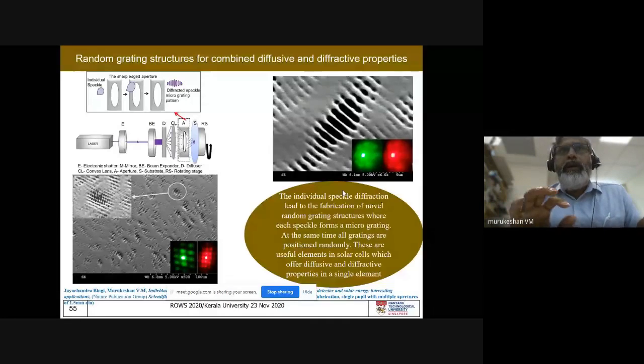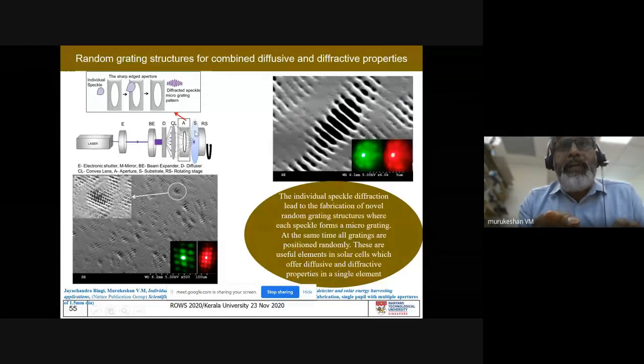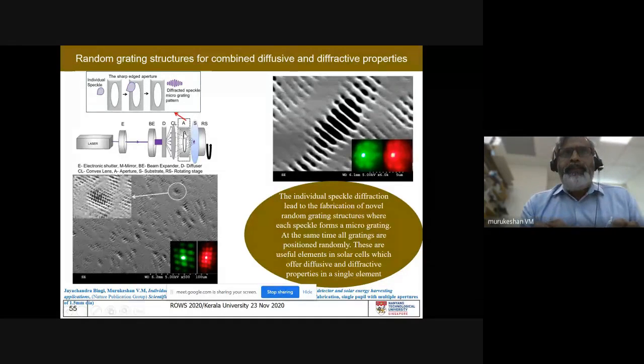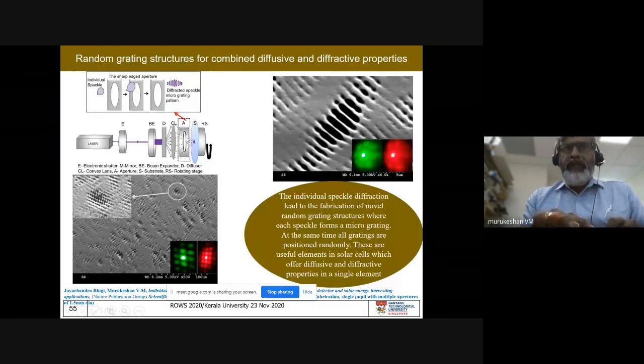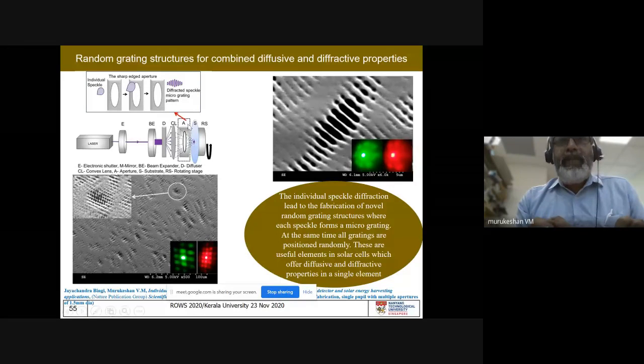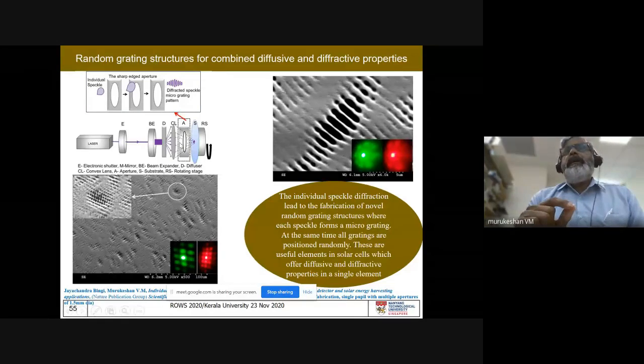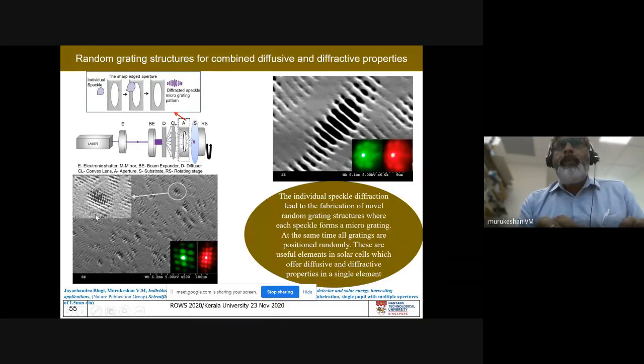Okay, the other one, what we have done is we again started changing or designing this aperture in a very special manner. The aperture dimension is changed in such a way that the thickness is reduced to a few hundred nanometers. When the thickness was reduced, we found that there is actually a diffraction occurring there, and this is going to create a very random oriented diffraction pattern. When you use a single aperture, this is what you are going to get. And if you change this pupil with multiple apertures, with the dimension of the aperture edge being very, very thin, then you are going to get 2D gratings.